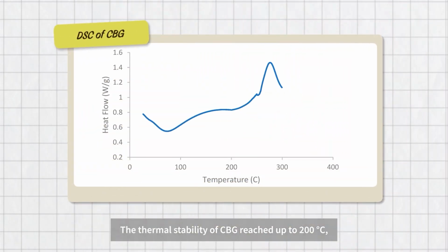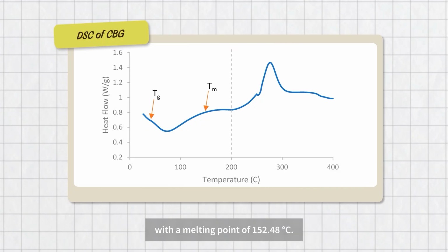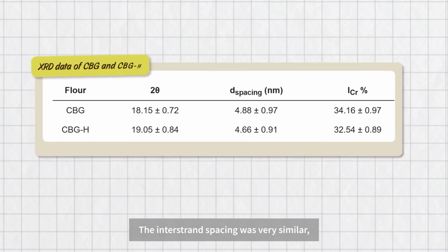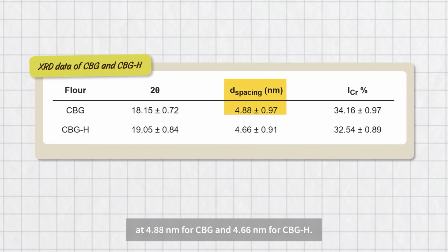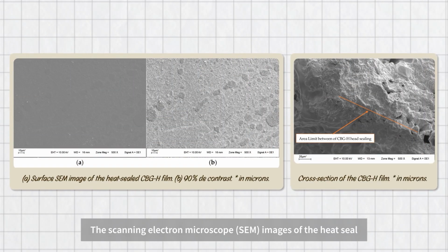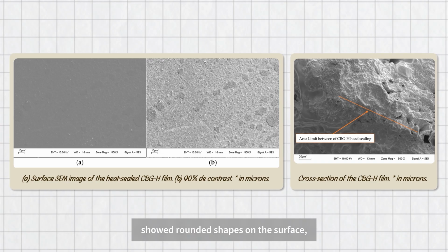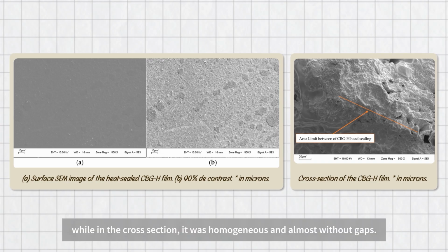The thermal stability of CBG reached up to 200 degrees Celsius, with a melting point of 152.48 degrees Celsius. Their interstrand spacing was very similar, at 4.88 nanometers for CBG and 4.66 nanometers for CBGH. The scanning electron microscope images of the heat seal showed rounded shapes on the surface, while in the cross-section it was homogeneous and almost without gaps.